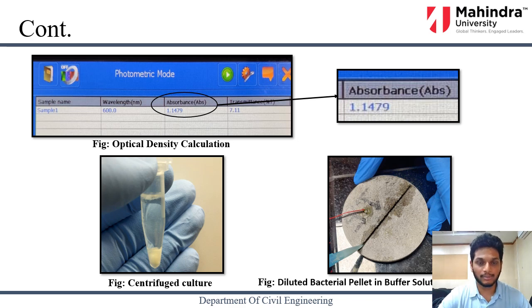We adjust the concentration of the bacteria by centrifuging it and adding a buffer solution. The buffer solution is there to protect the bacteria which are going to be induced in a high alkaline environment, which is the concrete specimens. And the reason for us to choose the Bacillus bacteria is because Bacillus bacteria usually show a property known as biomineralization. Biomineralization is a property exhibited by microorganisms, where small microcrystals are deposited in the matrix of the living organisms. And this deposition of minerals, which in our case is calcium carbonate, is very helpful in healing the concrete. That is the reason why we chose Bacillus bacteria.